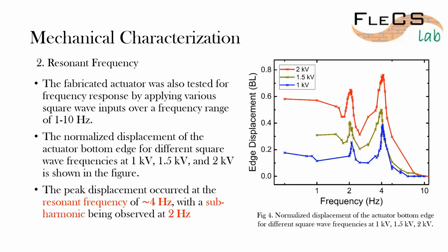I don't have a video of it right now, but it really tries to move, and you can see that because it's an elastomer, the mechanical, viscoelastic forces are not allowing it to move at 10 hertz, or actually not even at 10 hertz, even at 8 hertz or so, it kind of dies. But at 4 hertz it's reasonable, and we're okay with that, because if you look at your muscles as well, a simple experiment is to try to do this as fast as you can. I'm guessing you'll not be able to hit 10 hertz. So we are okay with whatever actuation we were able to get.